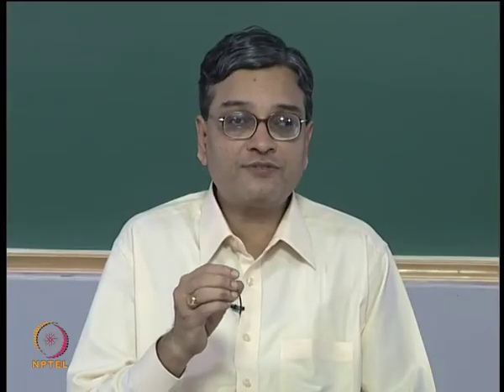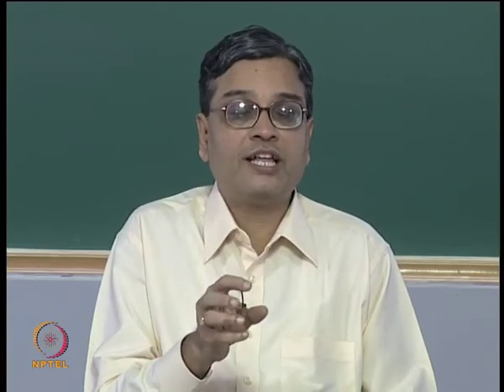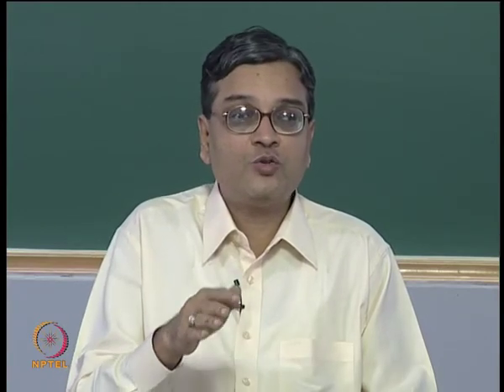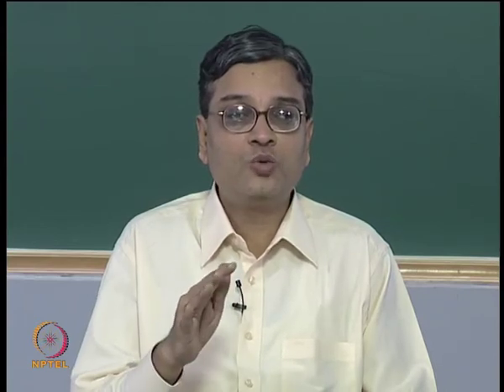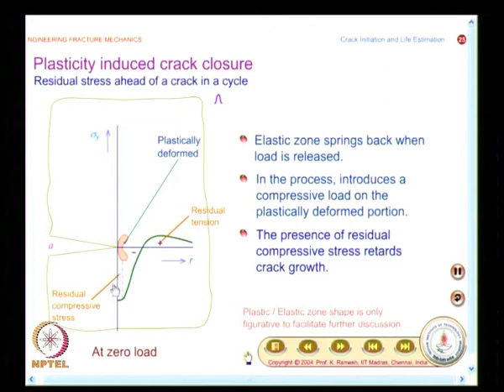You know, in a normal component, when you load and unload, you do not have residual stresses developed. In the case of a crack problem, what you find is, because of singularity, the stresses are very high and the material has gone to the plastic zone in the near vicinity. So, when you unload, you have formation of residual stresses, and this is very, very fundamental. If you want to appreciate crack closure, or if you want to appreciate the retardation effect due to overload, you will have to recognize that there would be a residual stress ahead of the crack tip because of loading and unloading. And very close to the crack tip, it is compressive stresses, and a little distance away, you have residual tension.